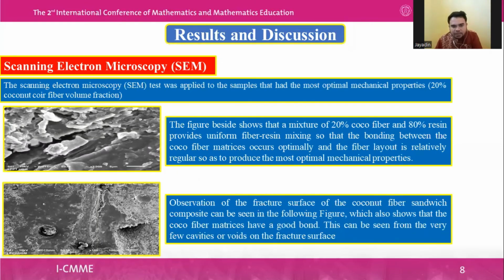Observation of the fracture surface of the coconut fiber sandwich composite can be seen in the following figure, which also shows that the coconut fiber and matrices have a good bond. This can be seen from the very few cavities or voids on the fracture surface.